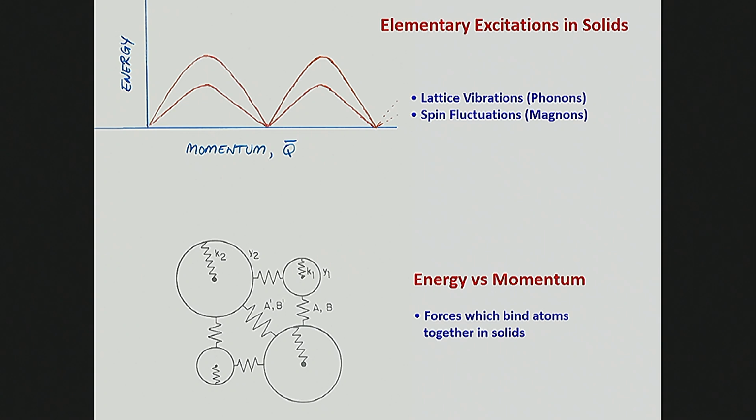And you'll have what are referred to as normal modes. And those normal modes will have a particular energy versus momentum relationship, which will depend in detail on these springs that we put in here. So if you can understand these energy versus momentum relationships, if you can understand how the crystal absorbs energy from either a neutron or from its environment, you can understand what forces are at play between the atoms. And that's what we're really interested in: understanding microscopically what's going on in our samples. So that's what we're really trying to get at.